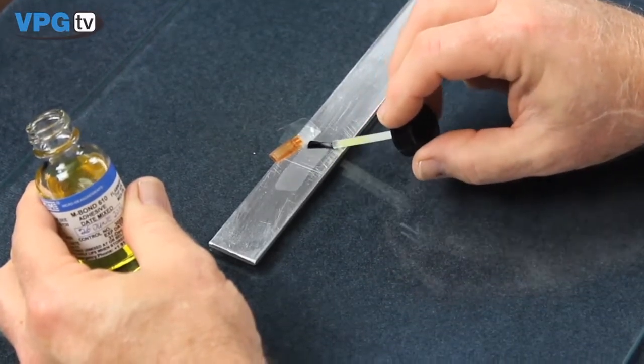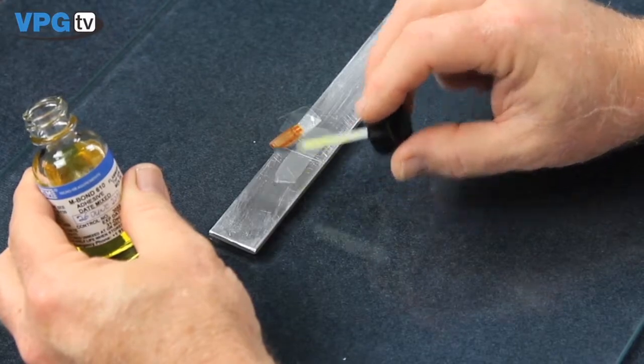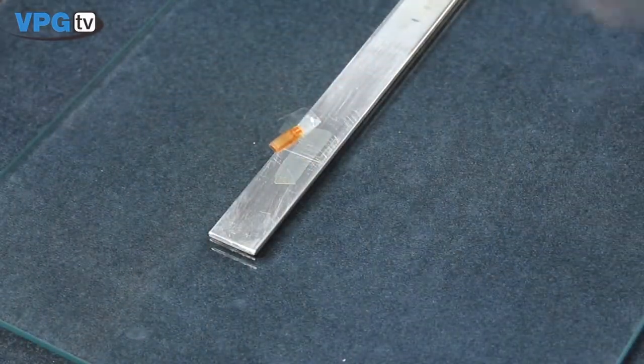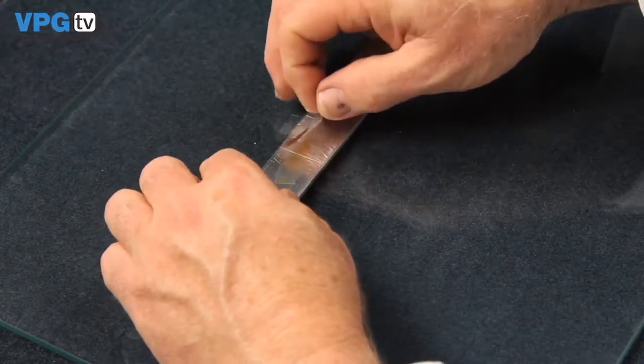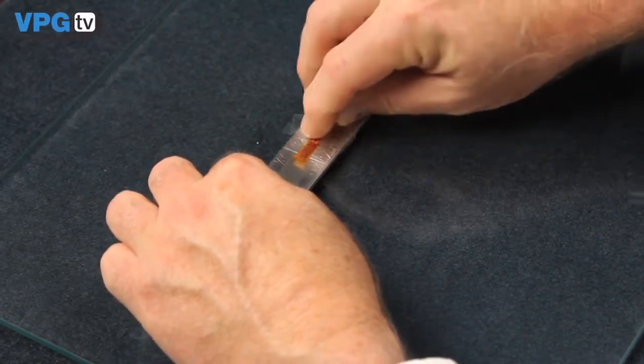Leave the bonding surfaces exposed to air dry for at least five minutes, but no longer than 30 minutes for M-Bond 610. Smoothing the tape down, reposition the strain gauge in the desired bonding location.